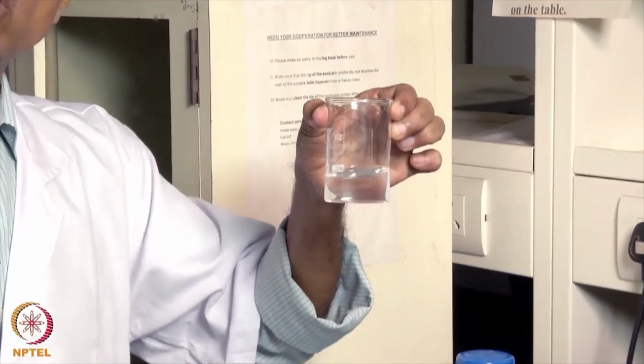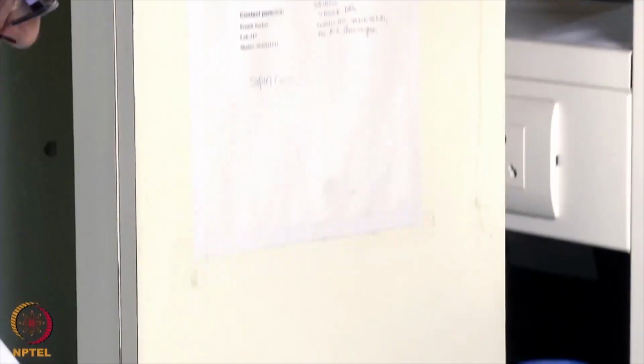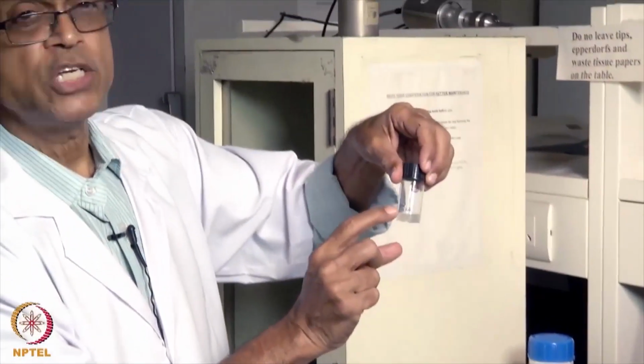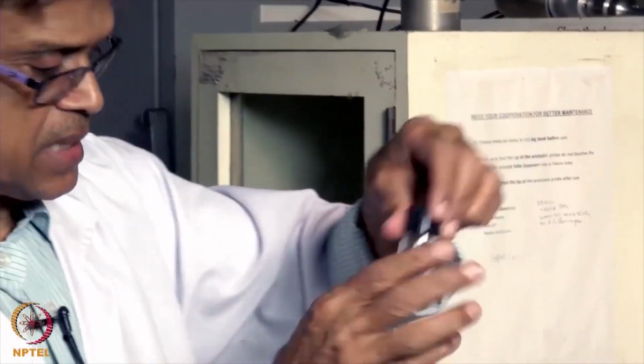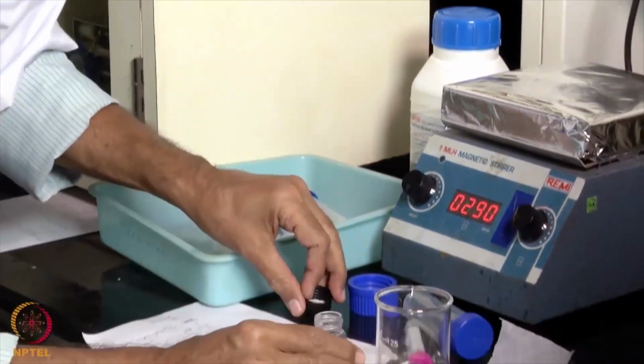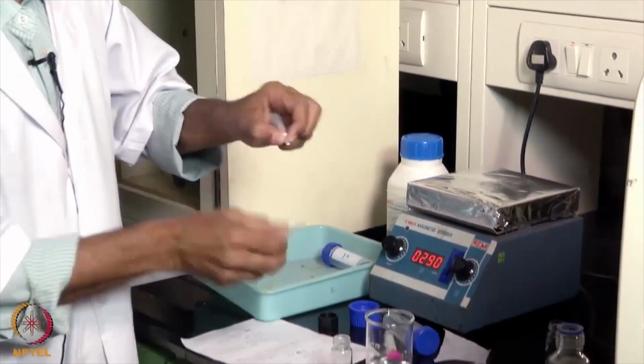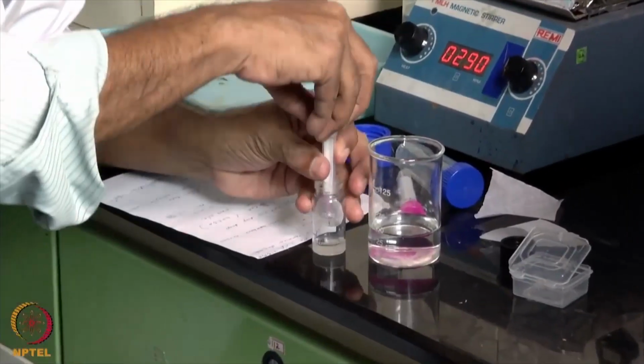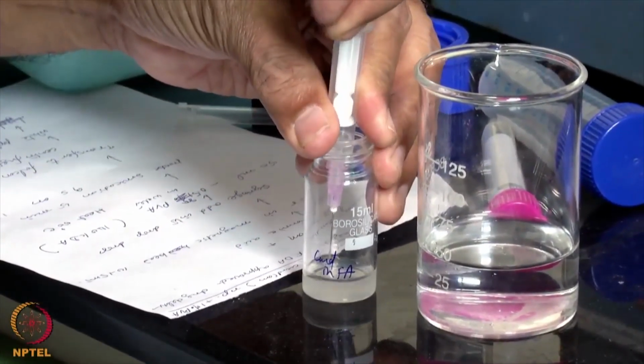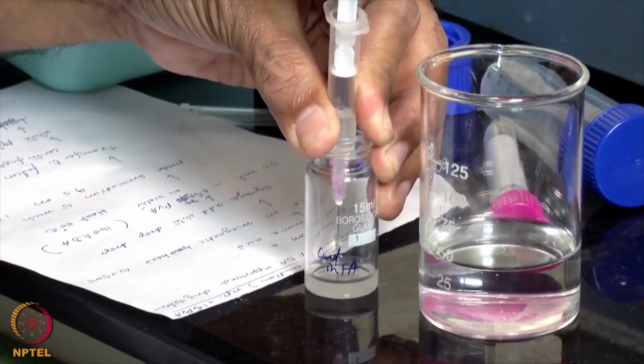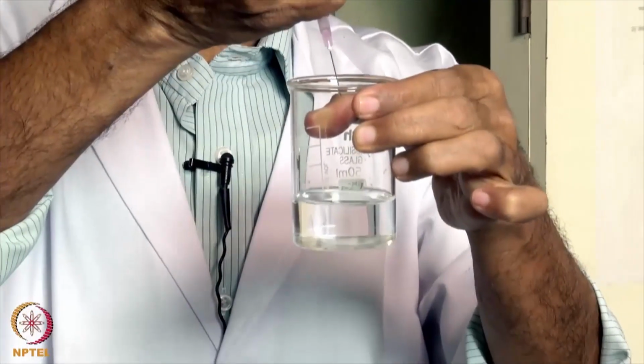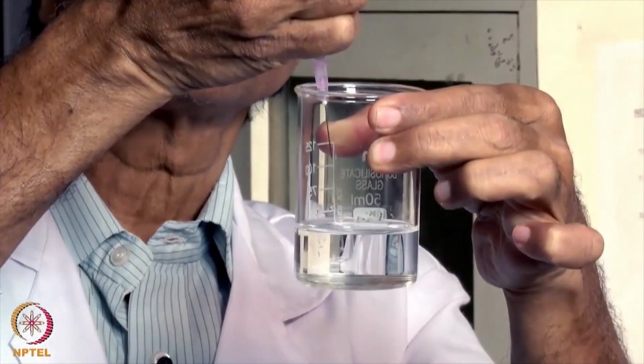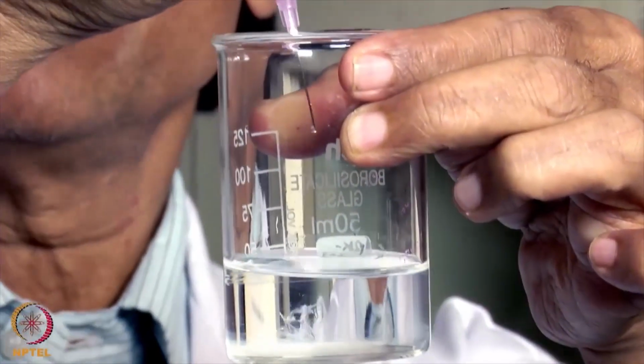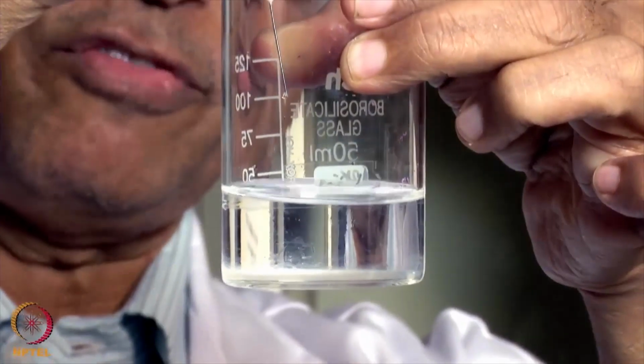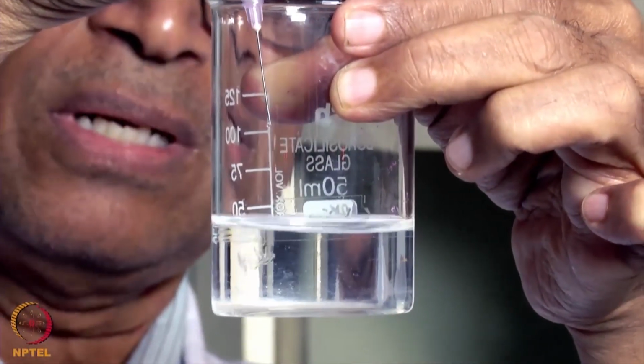Now I transfer this PVA solution. Now I need to add the beta glucan in formic acid dropwise using a syringe into this. Okay, so I have previously prepared beta glucan in formic acid. As you can see here, beta glucan in formic acid. So now I will take it in a syringe. As I said, PVA will try to stabilize the nanoparticle. As you can see here, small white, that is the nanoparticle of beta glucan. Can you see this?